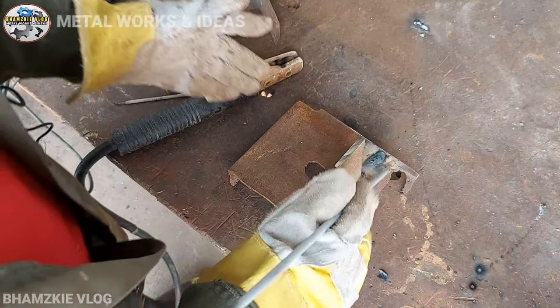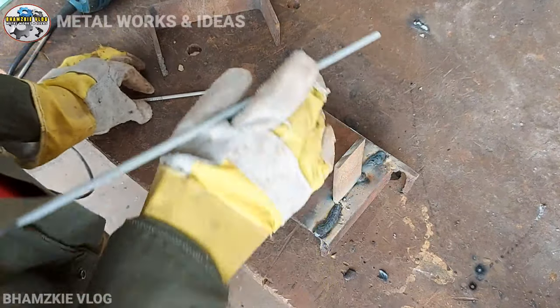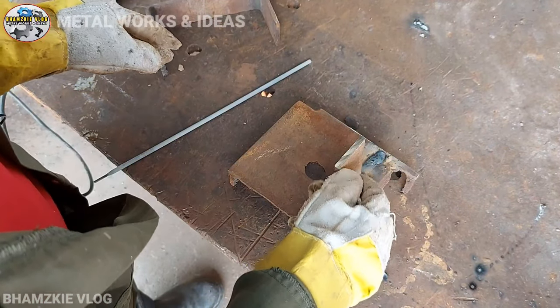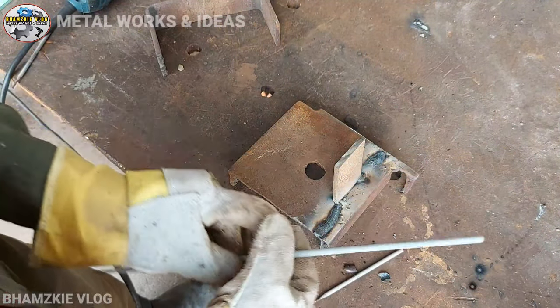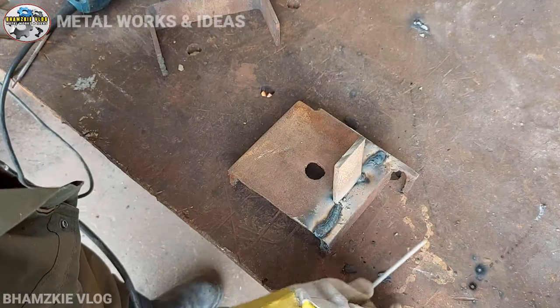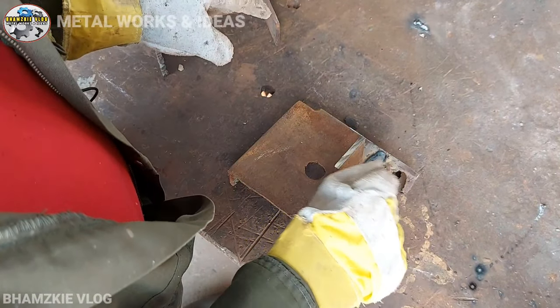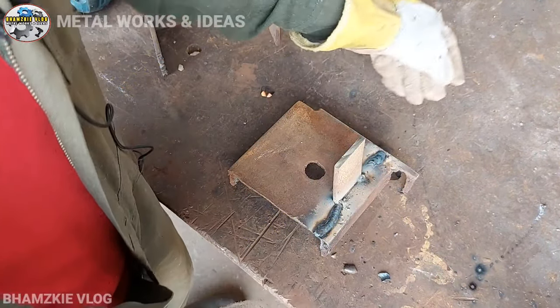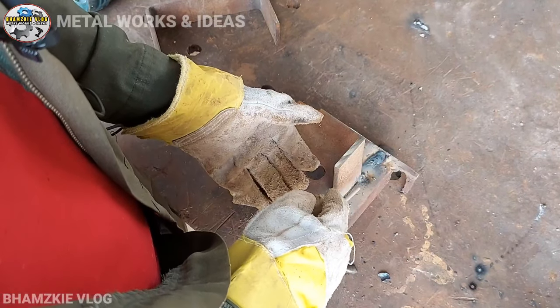Kadalasan ay sa una nating pag-welding ang problema kasi minsan hindi pa natin alam yung adjustment ng ating machine. Sa simula, didikit-dikit talaga yan kasi hindi mo pa alam yung adjustment niya. Pagka ganyan mangyari at dumidikit-dikit, taasan mo lang kunti yung amperahe. Kilalanin mo yung welding rod na iyong ginagamit — kasi may sarili-sariling amperahe ang bawat rod. Ito — 2.4 at 3.2. Yung ginamit natin ngayon ay 2.4 sa 85 amperes, hindi na siya dumidikit-dikit. Yung pagdikit-dikit ng welding rod ay normal din — mangyayari talaga yan kahit sa sinong magaling na welder. Dumidikit talaga yung welding rod. Kaso, pagka alam mo na yung pagkukontrol ng inyong kamay, madali mo na siyang ma-avoid.